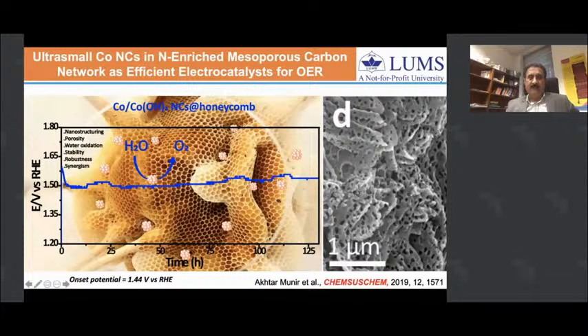Here we generated cobalt nanoclusters in a nitrogen-enriched mesoporous carbon network. Within the pores of this mesoporous carbon, we generated cobalt nanoclusters, and again we found they were really extremely stable, maintaining their catalytic activity for OER, oxygen evolution reaction, under alkaline conditions for up to 4 or 5 days.